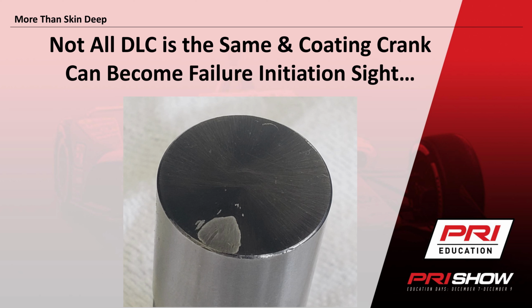And the surface has to be right. Like you see, this failed because there's too big a chamfer on the lifter, but the lifter itself was too rough to begin with. So if you put on a hard DLC, it's about 3,000 Vickers. The hardest steel is less than 1,000 Vickers. So paper, rock, scissors, it's going to win. So you put a DLC on a rough surface, it's a cutter. The other thing is the DLC is really hard, so you can't just DLC every material. You can't take a cast iron cam and a cast iron lifter, put DLC on it and think it's going to work. It's not hard enough. It's going to try to flex.